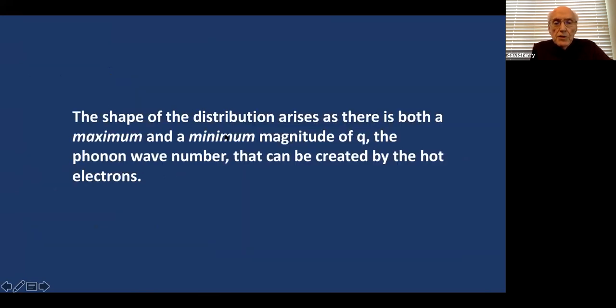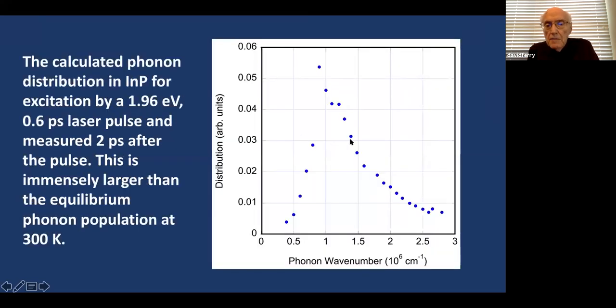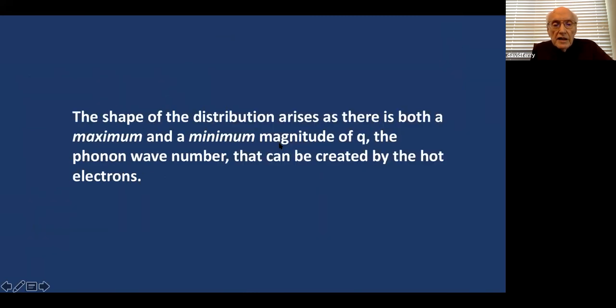Okay, so the shape of the distribution arises because when the electron interacts with the phonon to emit the phonon, there's a maximum value of phonon wave number and a minimum value of phonon wave number that you can interact with. And that's because of conservation of momentum and energy that's in the Fermi golden rule. And so that maximum and minimum are separated roughly by the width of this peak. And you can see 1 is 10 to the 6th per centimeter wave number. So the phonons are 2 orders of magnitude bigger. So they sit at gamma. Okay, so